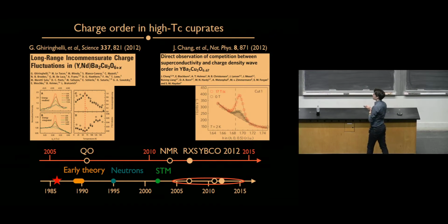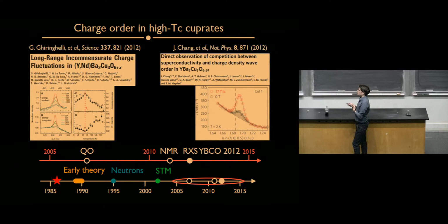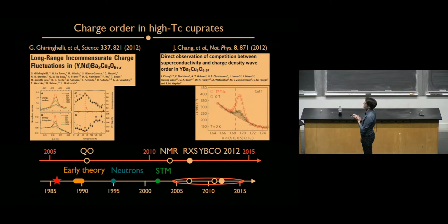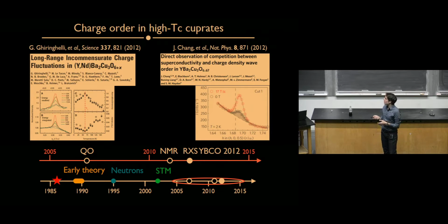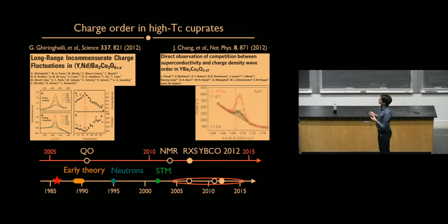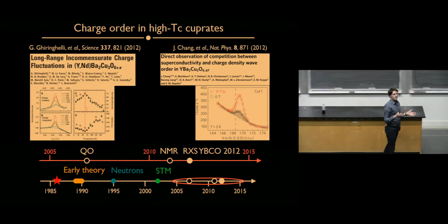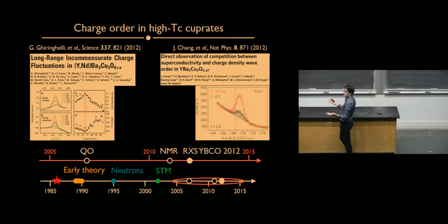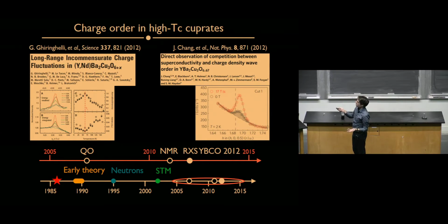And more recently, charge order was then found in the same compound, YBCO, using resonant diffraction and also non-resonant diffraction. So you see this peak. This looks like the peak that I showed before in the introduction in the first few slides. So you have a peak at a wave vector of about 0.31, which corresponds to about 3 unit cells of wavelength in real space. And you can see this is the intensity of charge order. And it increases, and when you reach the superconducting temperature, it starts to drop. And this is a very direct indication that superconductivity and charge order are in competition. So when superconductivity kicks in, charge order gets weakened. So the amplitude or the strength of charge order goes down.